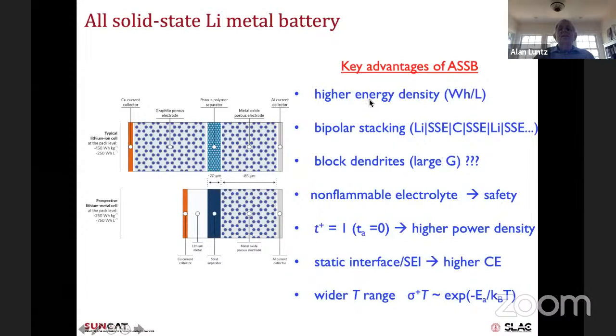But you can see immediately, just qualitatively, that this gets you a much higher energy density in watt hours per liter. In addition, because this is a solid, you can stack one on top of the other and get bipolar stacking. You can stack many together, and that also will help you get more energy density. You can't do that with liquids very easily because they'll run out. The other thing is, because these are stiff, they should block dendrites, but we'll come back to that issue, which is always possible. They're non-flammable, so you have a safety advantage. It turns out they're single ion conductors. The anions don't move, so this doesn't give you any concentration issues, and you can get higher power density.